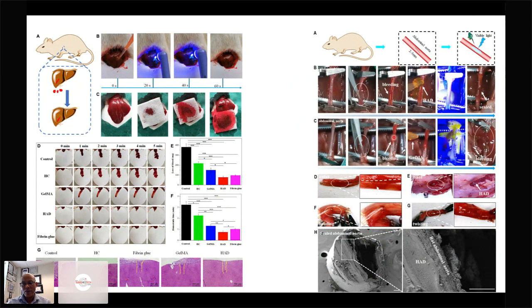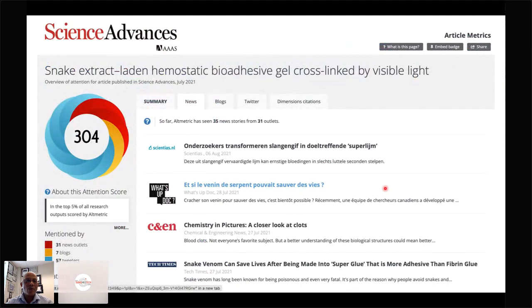we also tried it with arteries, and we basically ruptured an artery, and then blood is coming out, and then we apply the sealant, and we were able to demonstrate that this is quite an exciting material. So when this paper was published back in July, we were excited. It picked up a lot of momentum, and you can see some of the scores that have been compiled by the journal: it was in the top 5% of all research outputs scored by Altmetric, and it made news not only here in Canada, but in the US and in Europe, and even in other parts of the world, which was quite exciting.